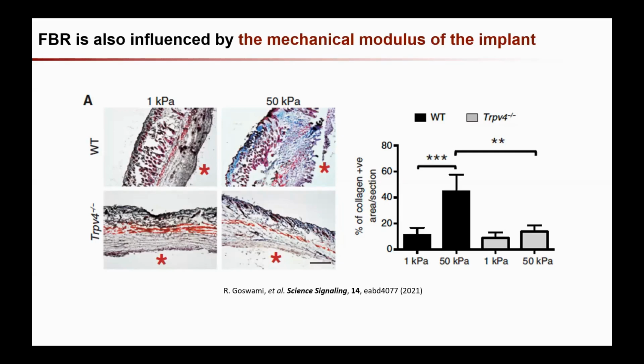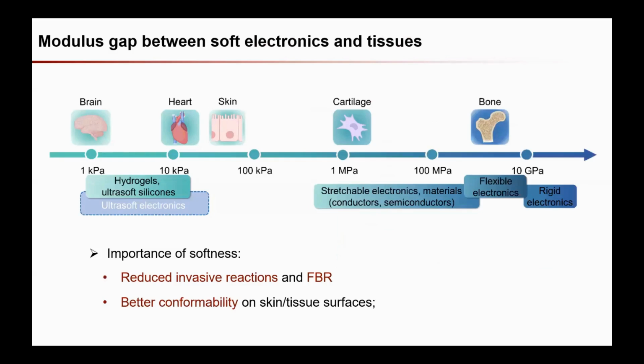The foreign body response from these two modulus levels actually still shows a big difference, with the lower modulus giving a much lower foreign body response. So that means for electronic materials and devices, we need to be able to get to that modulus range, very soft, similar to the tissue level.